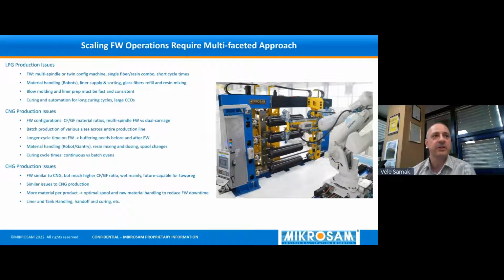If you're producing LPG today, you need a fast multi-spindle machine or maybe a twin machine. It's a single glass fiber resin combo, short cycle time. So you want this machine to run as fast as possible, and you want the liners just to come in there and occasionally replace the glass fiber and the resin into the machine. So here the issue is how do you arrange the curing and the automation for the curing? So now you can have one or two winders with 4 or 5 spindles, but very large continuous curing ovens.